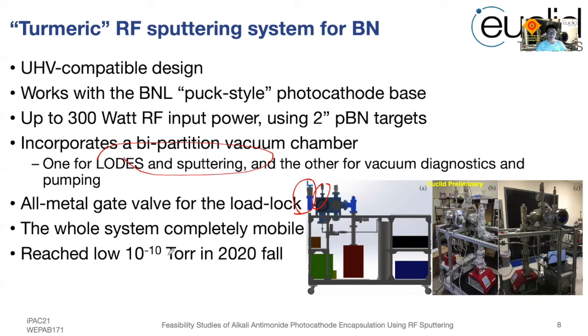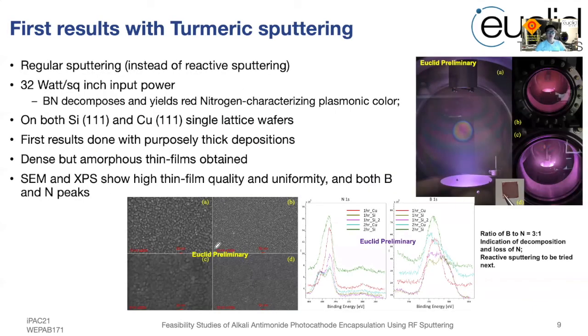It reached low 10 to the minus 10 torr in 2020, but unfortunately, because of COVID, the system was never used at BNL with real photocathodes. However, for the boron nitride sputtering, we were able to do that in-house at Euclid. So you can see the plasma has been activated, and during a high power sputtering, the color turned a little red because of the decomposition and loss of nitrogen from the boron nitride target. We went to 32 watt per square inch input power for the nominal sputtering regime.